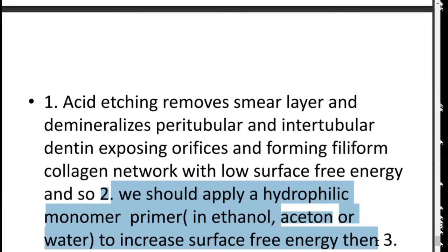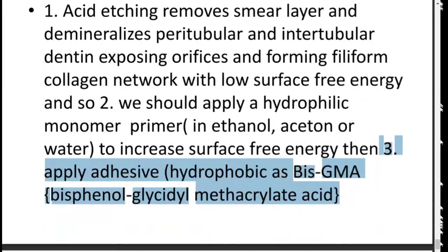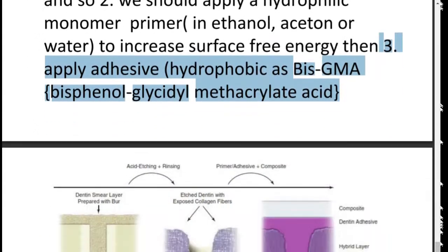Second step, we should apply a hydrophilic monomer primer in ethanol, acetone or water to increase free energy. Third step, applying adhesive, hydrophobic, as bis-GMA, bisphenol glycidyl methacrylate.